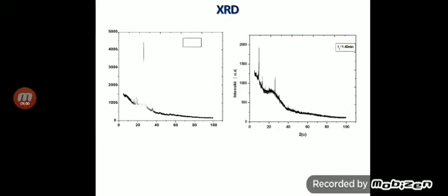Results and discussion. In the figures, we have reported the XRD diagrams obtained for the film products. In the films produced from the solution studied, as we can see, the deposition time of the thin layers influences the crystal structure of the films. A typical XRD pattern of the ZnS film grown by pyrolysis at 430 degrees C on a glass substrate.